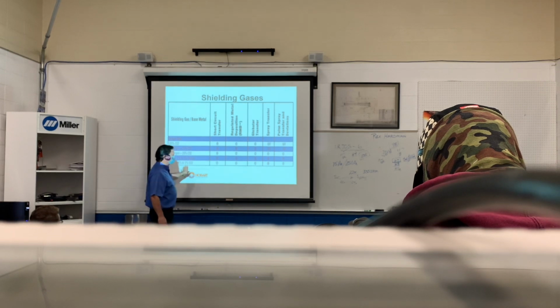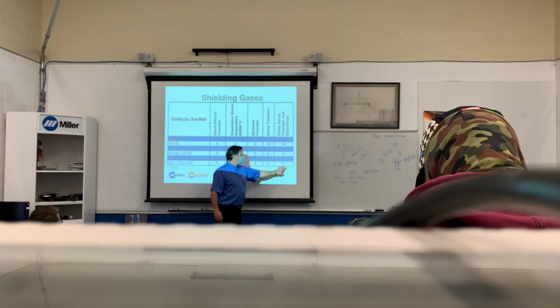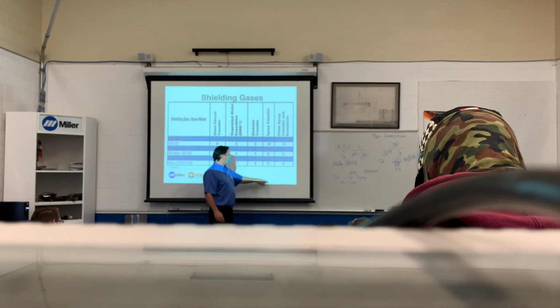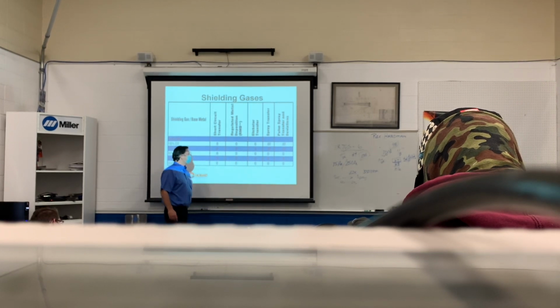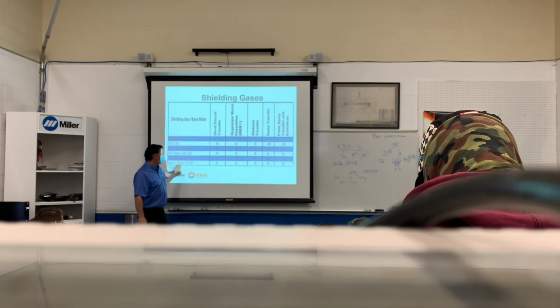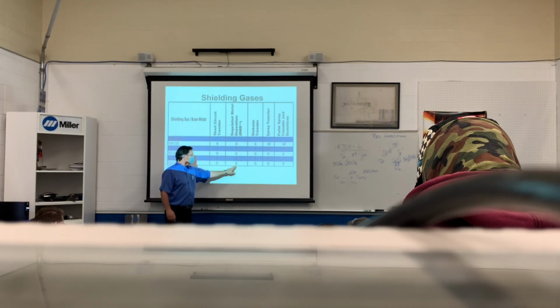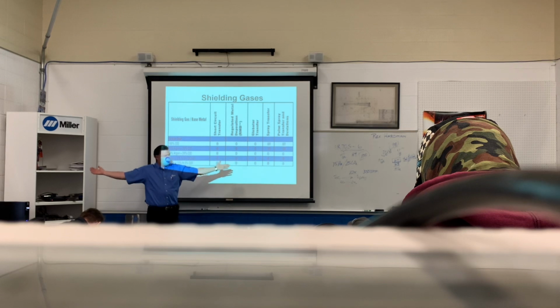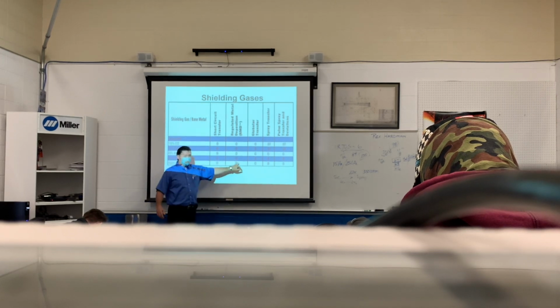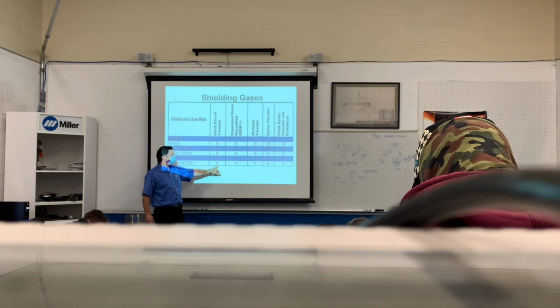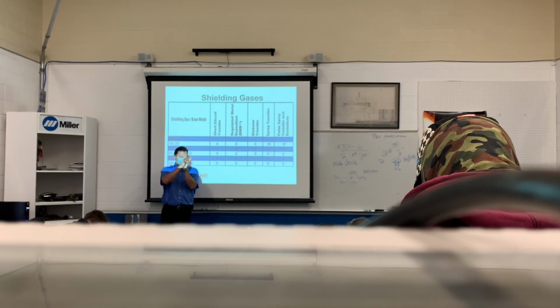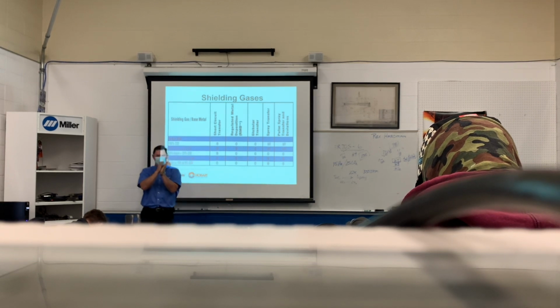The nice thing about 90-10 gas is that not only can I do my spray and my pulse spray, but I can do all these other processes too. Now keep in mind, when you get into a 90-10, globular right there, that window of operation is still huge. RMD actually works very, very good. But on the short circuit, your voltage window gets really small. You can still achieve a short circuit, but it's not going to be a very good window to achieve that.